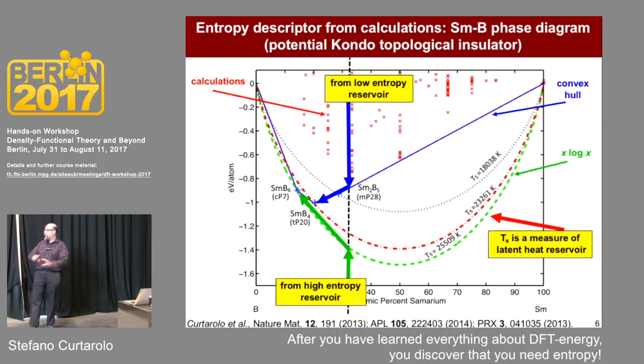Okay, the system, which is a chamber, gas, substrate, everything, we try to get rid of this heat, follow this equi-heat, which is the max entropy with respect to concentration locus, and eventually end up on samarium boron 6. So you see that the position of samarium boron 6, even if it's higher than samarium boron 4, it has a lower curvature. So you see the trick? If you change the system and you have the blue below the green and this blue above the red, the samarium boron 6 will not fall.